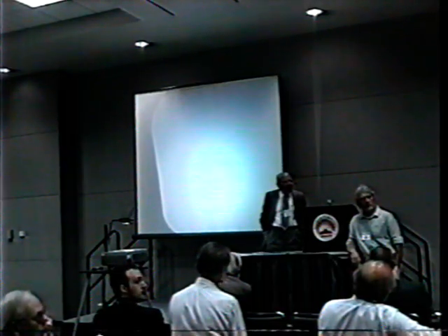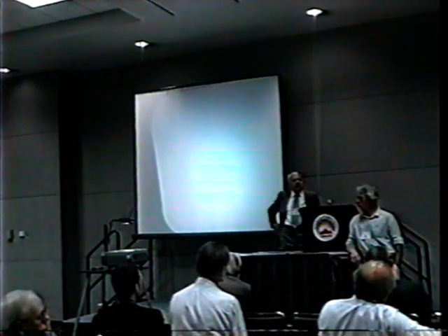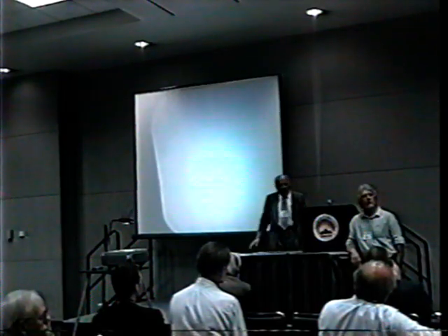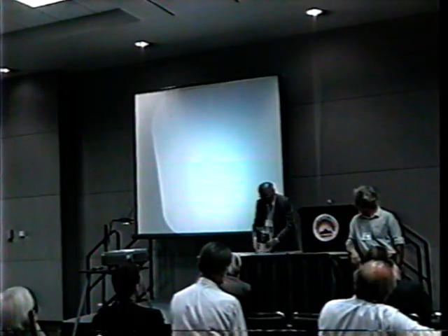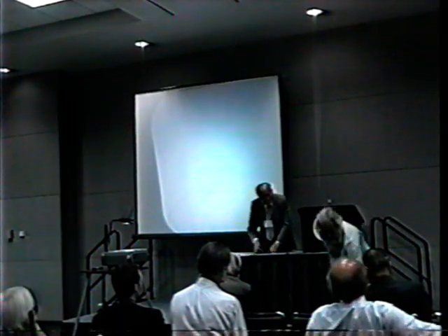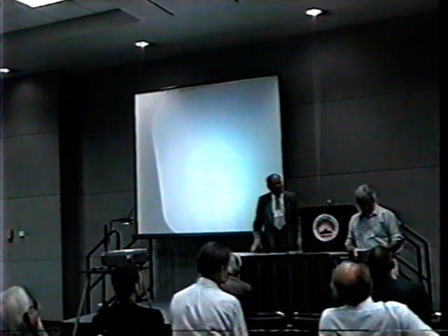The other question is, could you tell us the current density that you use during co-deposition? You said it's very low, but... Well, what we have done really, we control potential rather than current. So we start with some potential and increase it gradually. You remember that when you're absorbing hydrogen, you don't necessarily see its evolution. So you will see absorption long before the evolution. So you keep the current density low enough that you see no bubble evolution? That's right, yes. And then, of course, when you carry it out, the potential is high enough to make sure you're forming hydrogen. Yes.